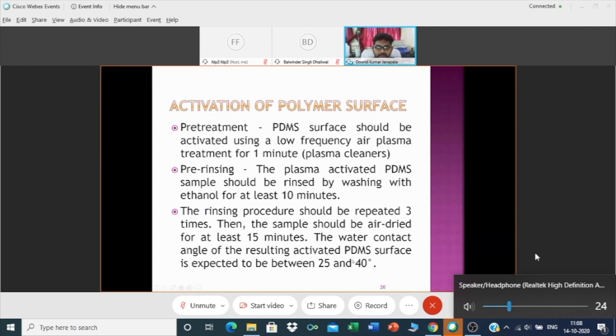Then you will get your angle. See here, 25 to 40 degrees. That means when you put your drop on top of it, if its angle is less, then that is good for coating. When it is super hydrophobic or hydrophobic, the angle of the water bubble will be higher, around 100 or something. That means you won't be able to coat it. So a water drop on top of this, hydrophobic and hydrophilic, will give you the understanding whether your particular polymer is activated properly or not.